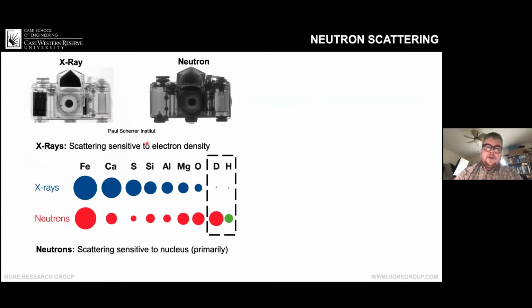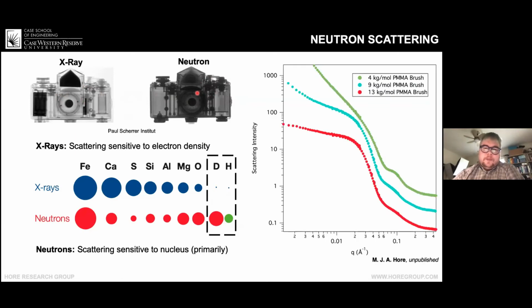Another advantage to neutron scattering is that whereas X-rays don't really respond or scatter much from light elements, neutrons do. And neutrons are sensitive to the isotopes, so deuterium and hydrogen scatter quite differently from each other. So we can get contrast that way. And just by eye, you can see the differences between an image taken with X-rays and an image taken with neutrons in terms of what absorbs and what doesn't absorb. So we can perform these measurements and we get curves that look like this. These are typical curves for polymer grafted nanoparticles.